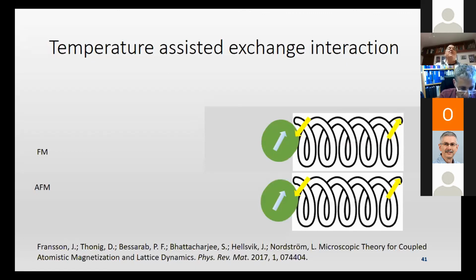And when they are moving towards the lattice, they spin polarize the lattice, because the charge on the cation attracts charge in the lattice. This charge that moves through the chiral lattice is now spin polarized. And as a result, the exchange interaction between the ion and the lattice becomes stronger.